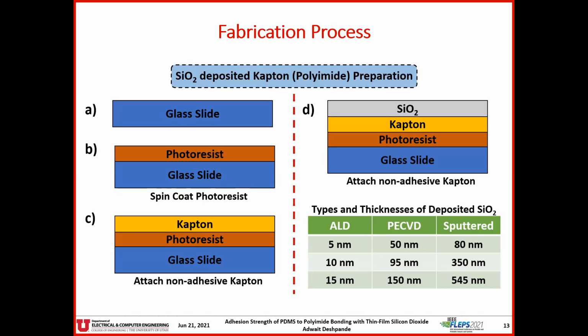The following steps were followed to create the SiO2 deposited polyimide samples. Photoresist was spin coated on a glass slide and then a non-adhesive Kapton was attached to it. This Kapton was 12.2 mm wide and 25.4 micrometers thick. This photoresist acted as a temporary adhesive layer.